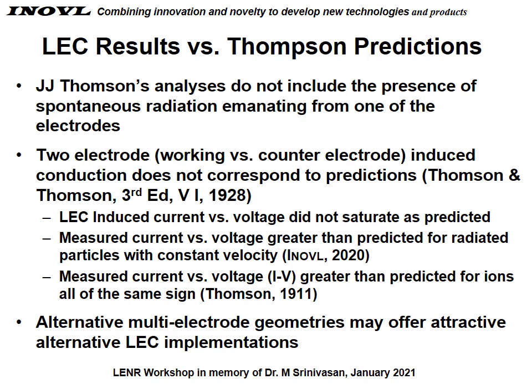In our two-electrode working electrode versus counter-electrode setup, where we induced a conduction by applying a voltage, it does not correspond to his predictions. The LEC-induced current versus voltage did not saturate as he predicted. The measured current versus voltage is greater than predicted for radiated particles with constant velocity, and measured IV is greater than predicted for ions of all the same sign. Alternative multi-electrode geometries may offer attractive LEC implementations.